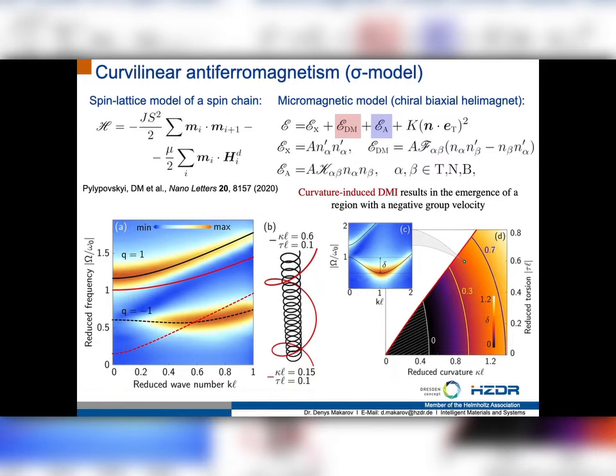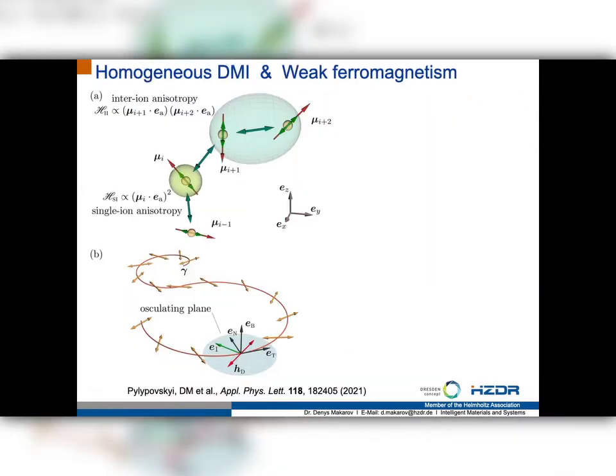a minima with a negative group velocity on the dispersion curve, which allows you to investigate also a collective interaction of magnons in exactly this minima of the dispersion curve, maybe even speculating about Bose-Einstein condensation in K-space, which is actually an interesting playground which is enabled by these very simple antiferromagnetic spin chains. Antiferromagnets are very rich because, compared to ferromagnets, they have many sublattices. In this case, you can have very interesting effects coming from exchange and also from anisotropy.